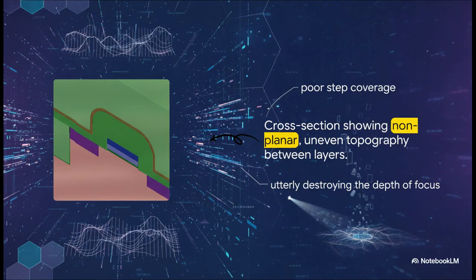When you look at this kind of cross-section, you can see how multi-level integrated circuits essentially copy the up and down areas from one level to the next. Every new metal layer just magnifies the bumps of the layer right below it. If you leave that unchecked, this nonplanarity becomes severe. It leads to poor step coverage of deposited films and utterly destroys the depth of focus that high-resolution photolithography tools need to print the next level.